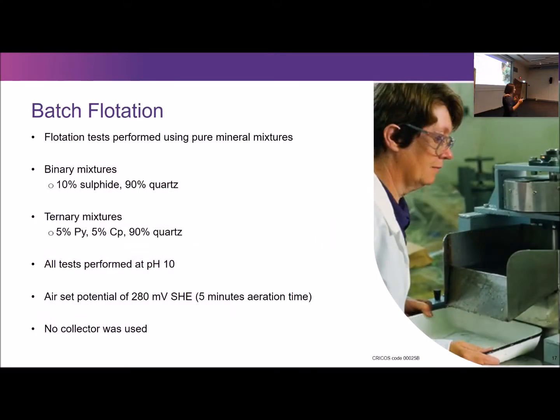Right. Batch flotation tests were then subsequently performed. I used both binary and ternary mixtures. In the binary mixtures, we had 10% sulfide, 90% quartz as your background inert gangue. And in ternary mixtures, 5% pyrite of both types and 5% chalcopyrite, 90% quartz.